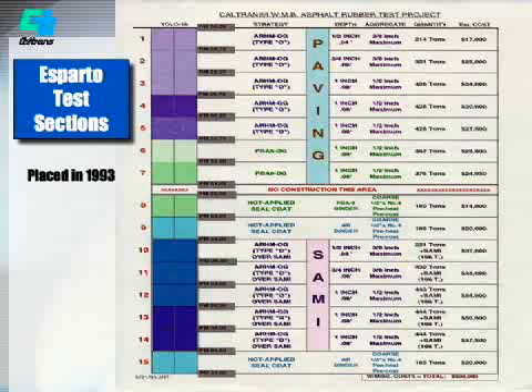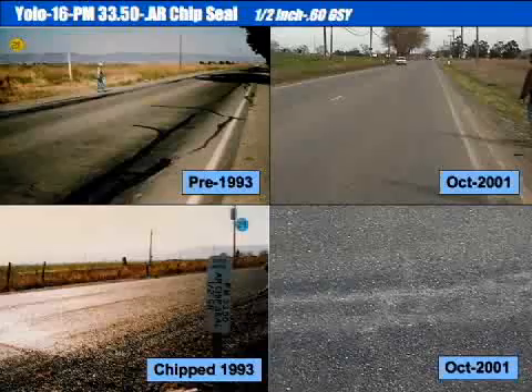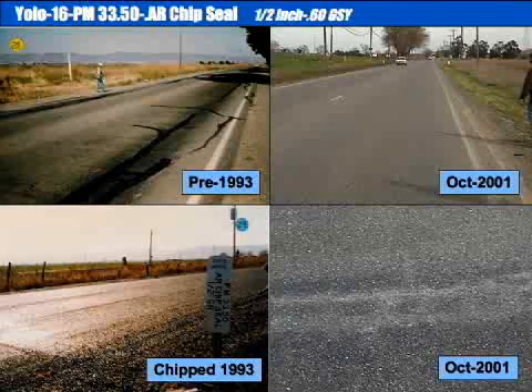Those test sections utilized various types of strategies: open graded, gap graded, chip seals. We used SAMIs, stress absorbing membrane interlayers. Some sections were with SAMIs and some without, and with different thicknesses. And all of these strategies were very thin, like 25 or even 19 millimeters.